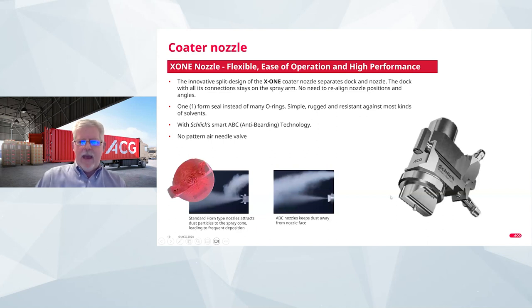The ABC cap, which I show you in this photo here, has a very different profile. And the pattern air, which is flattening out your spray pattern, does not form those same eddies. So you can see here, with a subsequent smoke generator, the smoke is not being drawn in, but it's being carried forward with the spray. And this leads to a much cleaner process, helping apply more of your coating to your product bed itself and less to the nozzle, spray arm, and other mechanical parts of the coater.